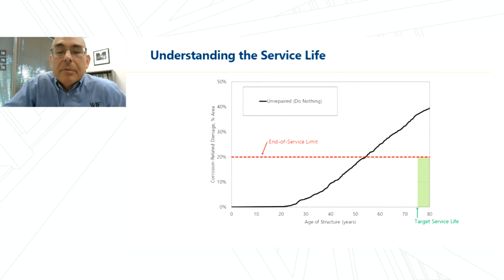The true end of service limit for any specific structure may be different. It may not be 20%. Time is shown on the horizontal axis with the origin representing the date of construction. And the heavy black curve represents the deterioration of the structure over time if no repairs or mitigation is performed. The target service life is shown on the right in green at around 75 years. In this case, the target service life is not achieved because the deterioration curve crosses the end of service limit between 50 and 60 years.